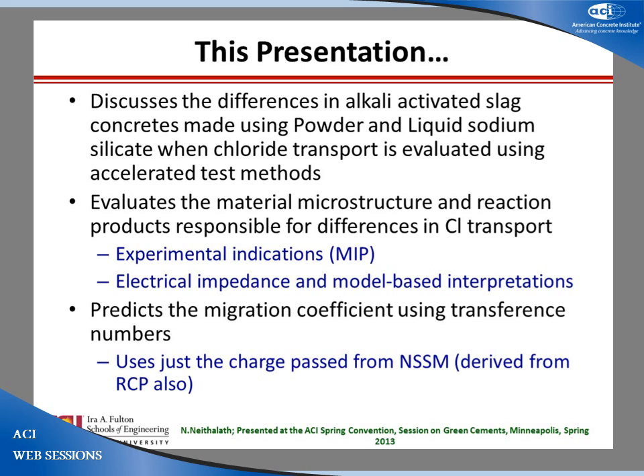So what we look at are material microstructure experimental studies using mercury intrusion porosimetry, and electrical impedance and associated model-based interpretations to show what is actually happening in the microstructure before and during transport. And then that gets you a simple method to predict the migration coefficient. And again, this is something that's universal. We have developed it for all types of concretes. I'm just showing the case for alkali activated concrete.